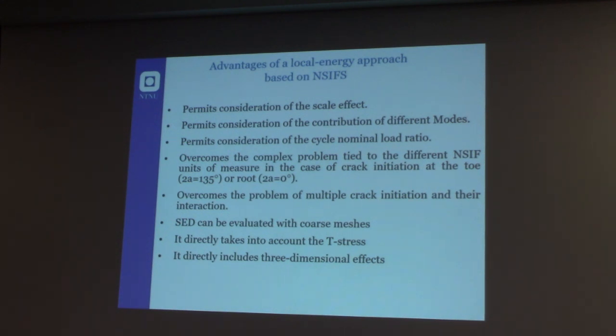And the second point is that the notch stress intensity factor is based on the stress field close to the notch tip. This means that it is a stress-based approach and not an energy-based approach.